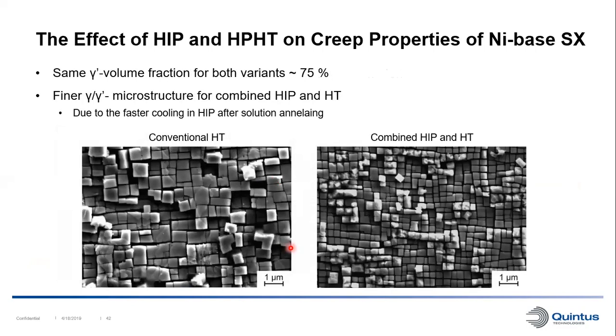Here we can see the results in terms of the microstructure. So we have the conventional heat-treated variant on the left and the combined HIP and heat-treated variant on the right. Both variants have the same gamma prime volume fractions, around 75%. But we can also see a difference here: the gamma prime microstructure for the combined HIP and heat treatment cycle is much finer. And this is due to the faster cooling in the HIP after solutionizing compared to the cooling in the gas quenching furnace.